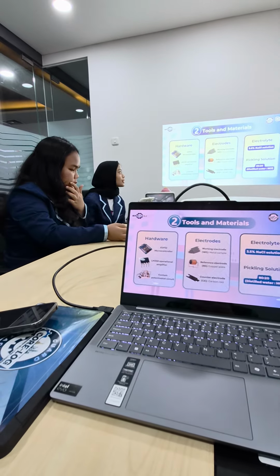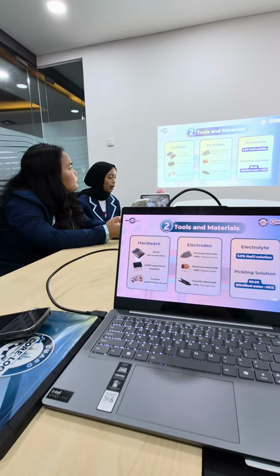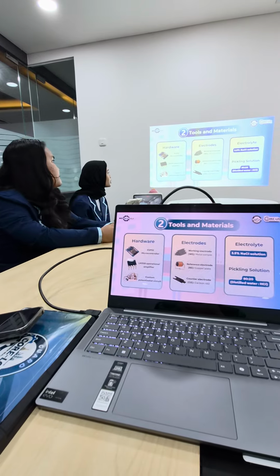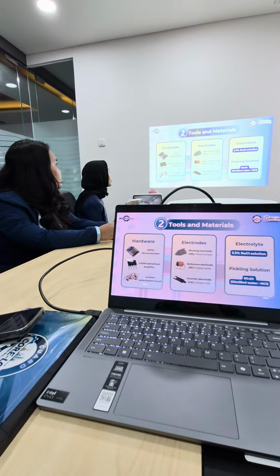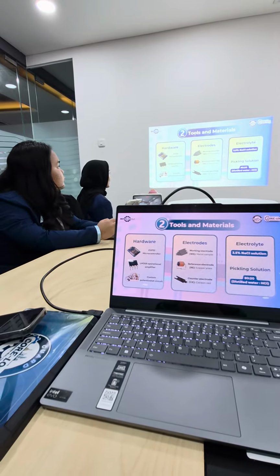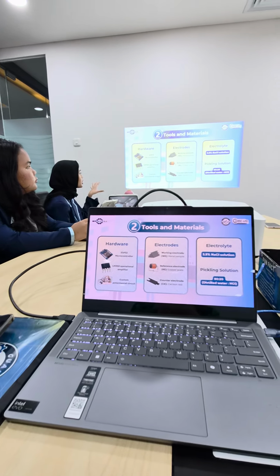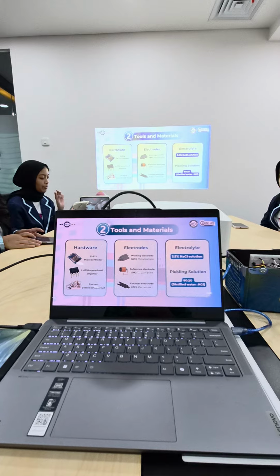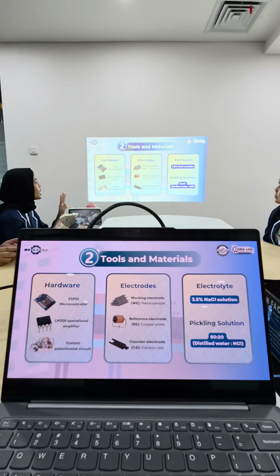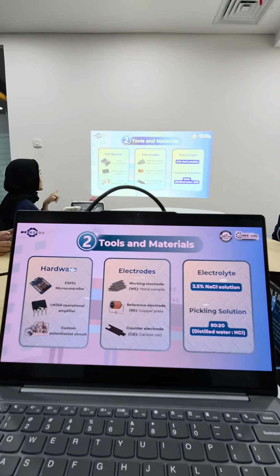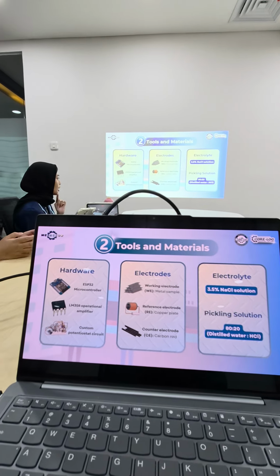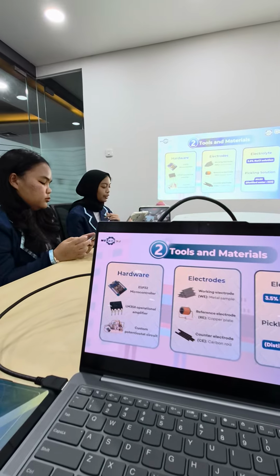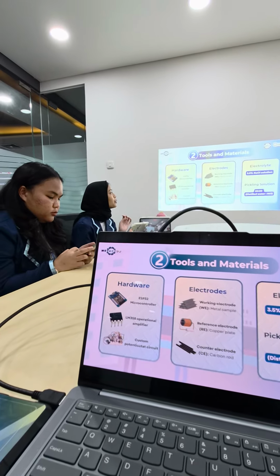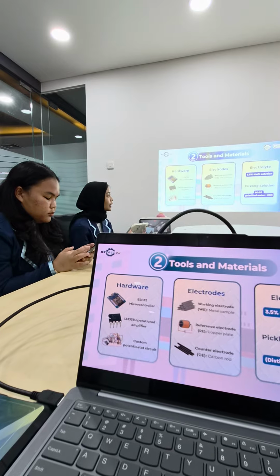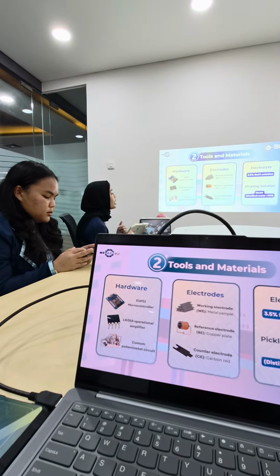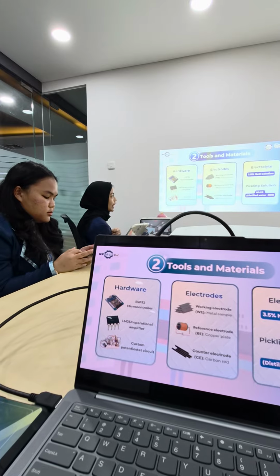Okay, now moving on to the tools and materials that we use for this research. Our hardware centers around an ESP32 microcontroller and an LM358 operational amplifier to stabilize the data, and all of these components were integrated into one custom potentiostat circuit. For the electrochemical cell, we use 3 electrodes: the metal sample being tested as the working electrode, a copper plate as the reference electrode, and a carbon rod as the counter electrode. For the electrolyte, to simulate the corrosive environment, we use a 3.5% natrium chloride solution, and also a pickling solution consisting of 80-20 distilled water and hydrochloric acid.